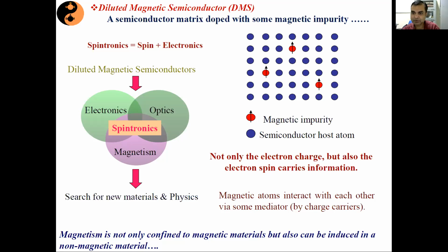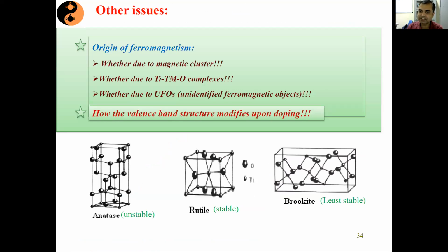Okay, so it's not only the electron charge but also the electron spin which carries the information, and these magnetic moments should interact with each other via charge carriers. So this is a very important thing. I do not want the magnetic impurity to form a cluster, rather they should be uniformly distributed in the system. And with that idea in mind, we started doping iron in titanium oxide. We know that titanium oxide is a semiconductor and non-magnetic in nature, but with iron doping, can we induce magnetization and have a spin polarized carrier?